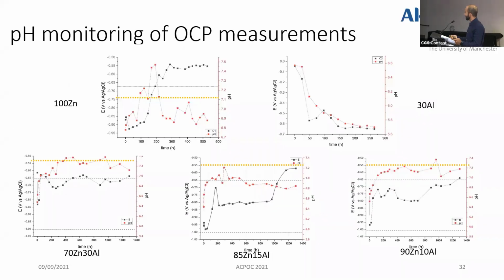The pH monitoring here was done to see what the pH trend is. So it starts rising at the beginning, and this is because the zinc dissolution, which is the anodic reaction in the coating, is balanced with the cathodic reaction of oxygen reduction, which produces OH minus. So the pH of the media is increasing. And as we know, aluminum in its normal state is passive, but when the pH is increasing, it starts to dissolve and offer some galvanic action. And this is the pH of the media. So I think the local pH inside the coating is a bit higher than this pH here.